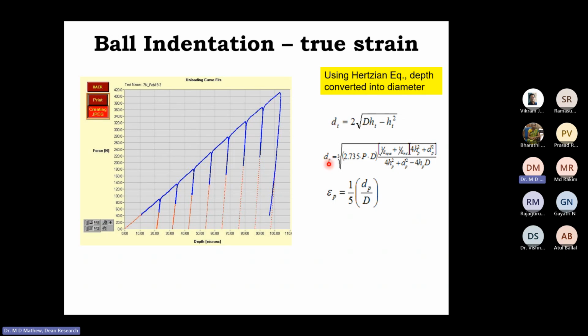And from that value, we can get the total diameter, which will consist of elastic and plastic parts. So by applying certain Hertzian equations, we can convert this total diameter into plastic diameter. And once we have the plastic diameter value, then you can determine the epsilon P, the plastic strain in uniaxial tension, using this equation. Epsilon P is equal to 0.2 dP by capital D, where dP is the plastic diameter and capital D is the diameter of the indenter. So now you have got the true strain as you would derive from a tensile test.